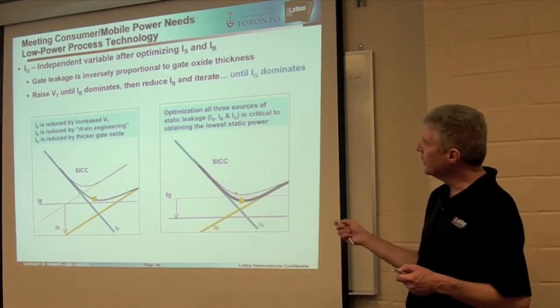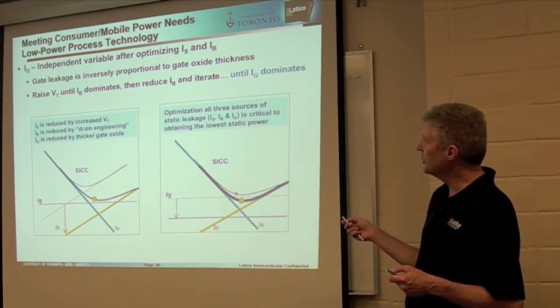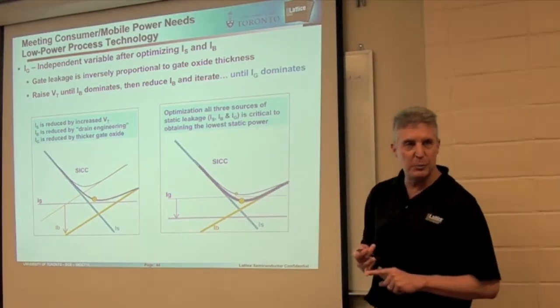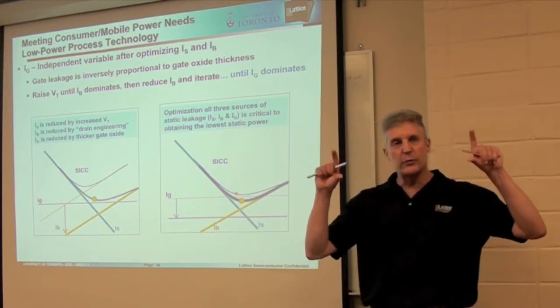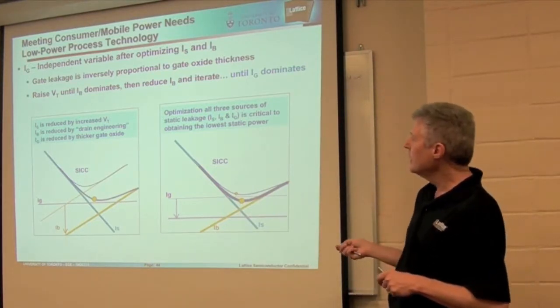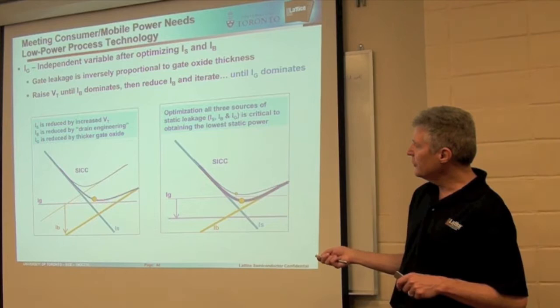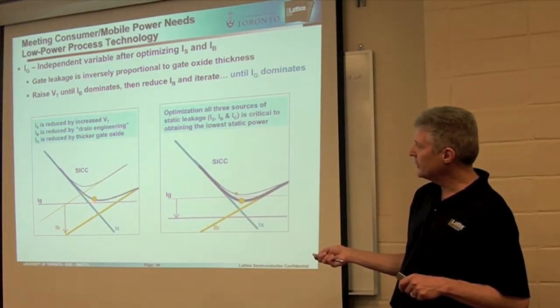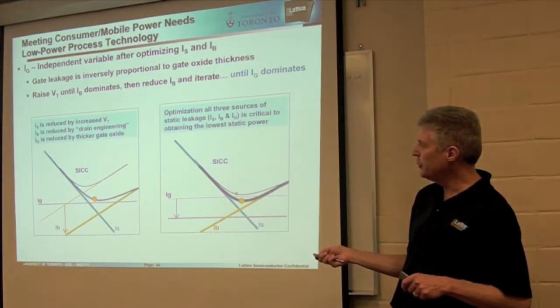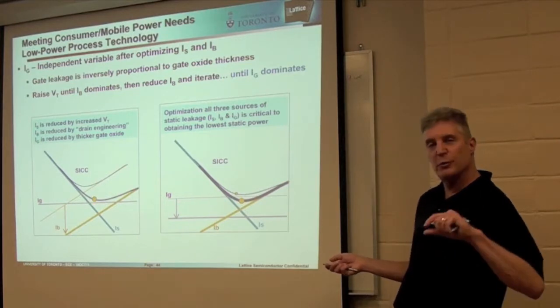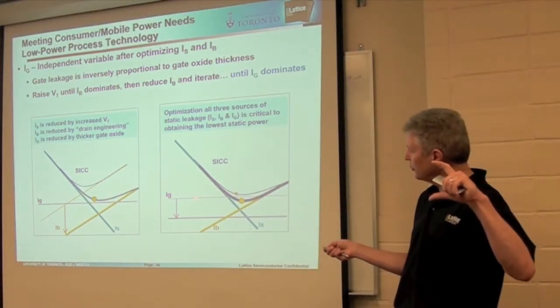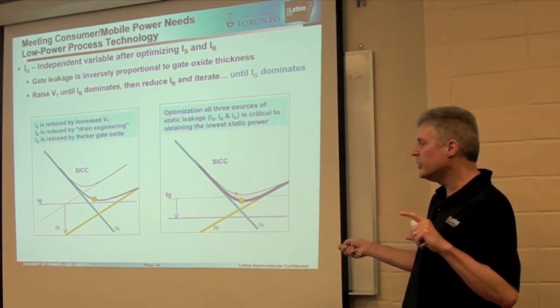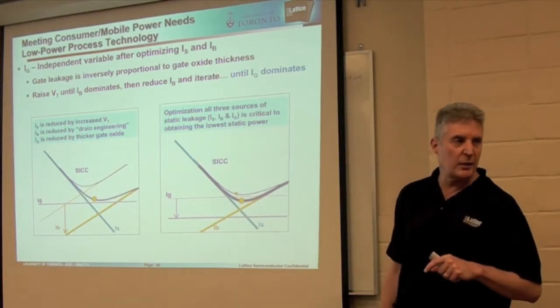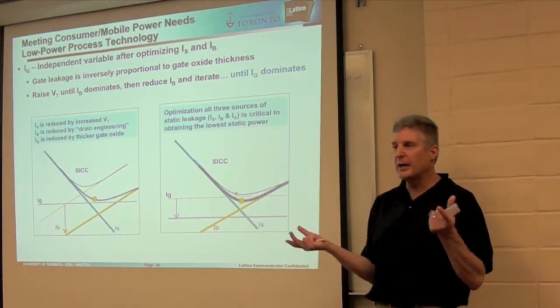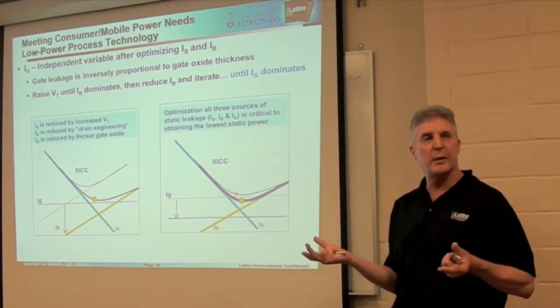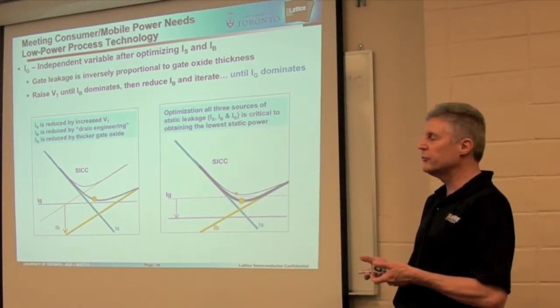Now finally, the gate leakage is an independent variable, and it really doesn't have a temperature dependence or a process dependence other than the thickness of the gate oxide, as we said. And so if you get to the point where the gate oxide leakage is going to become dominant, if you go down much further, what you want to do is increase your gate oxide thickness so that your leakage goes down, and again you continue to scale and get lower static leakage overall. So it's a balancing game, optimizing these three parameters to make a very low power transistor process.